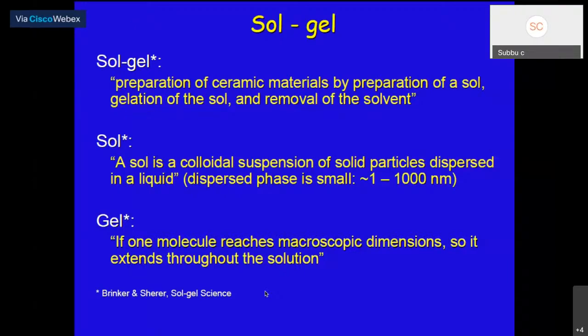I allow it to proceed, but I don't allow it to precipitate. I don't go to a pH condition where the ionic product exceeds the solubility product. When do you see a precipitation? Precipitation forms when the ionic product exceeds the solubility product. So I don't allow that condition to happen, so that I am always in a gelling stage, a semi-gel kind of stage.